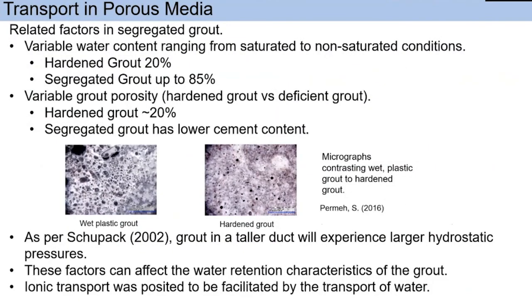It is possible that the transport of water and ions are related to the development of grout deficiencies, in part relating to hydrostatic pressure. These are other related factors in segregated grout. Water content: in hardened grout, we had 20% water content. In segregated grout, it was up to 85%. Grout porosity in hardened grout was nearly 20%, and segregated grout has lower cement content. In these pictures, you can see the wet plastic grout has larger porosity than the hardened grout. In 2002, Schupack stated that the grout in a taller duct will experience larger hydrostatic pressure. These factors can all affect the water retention characteristics of the grout.